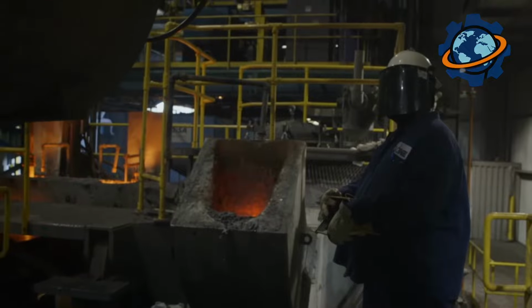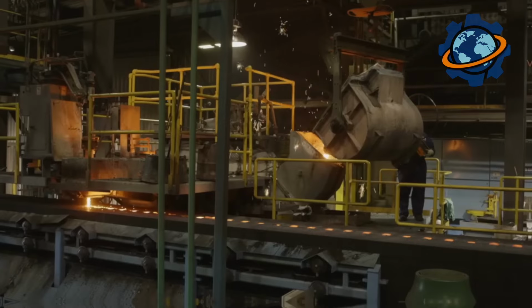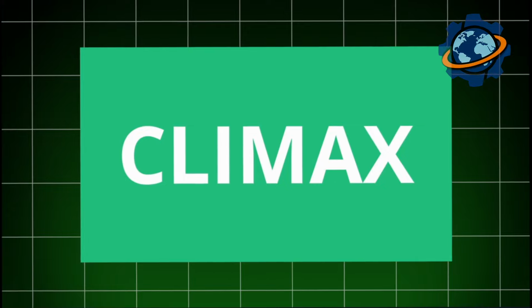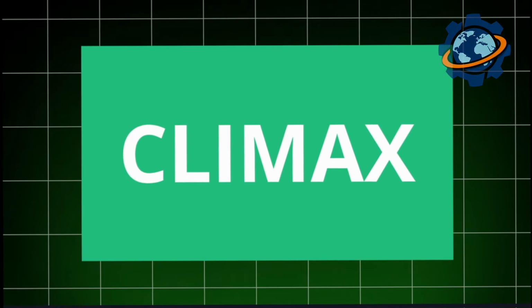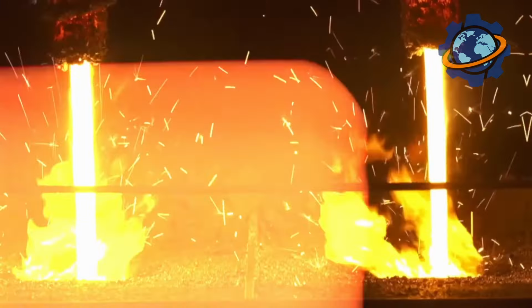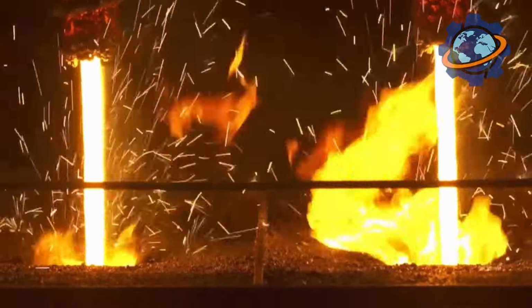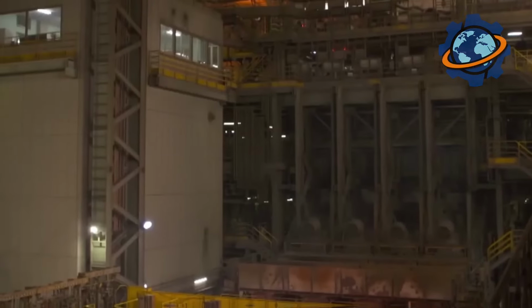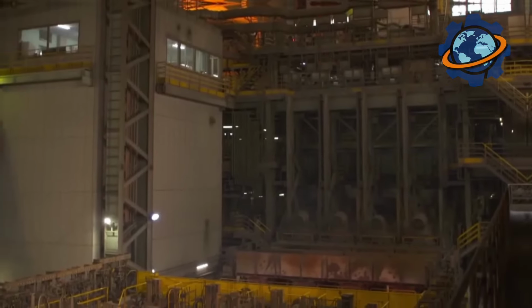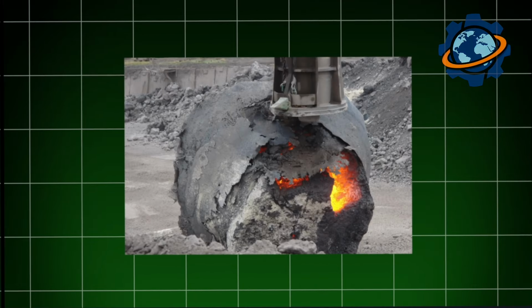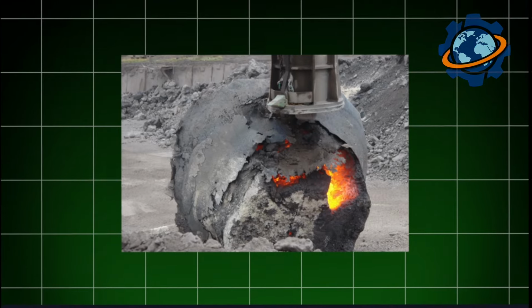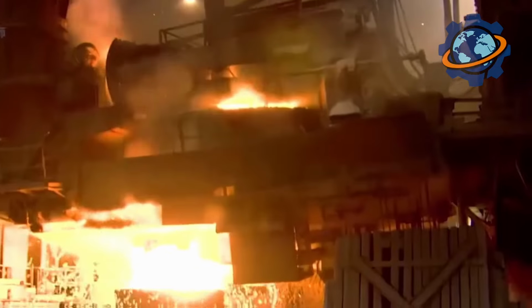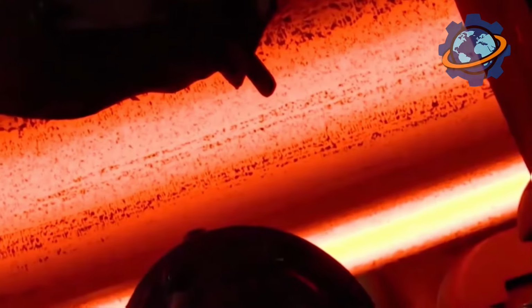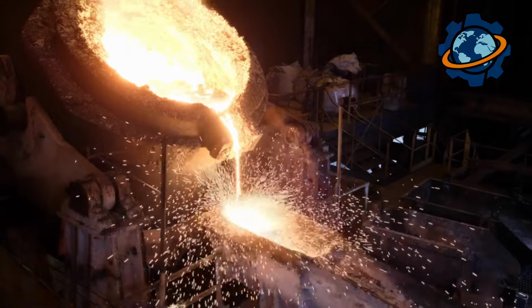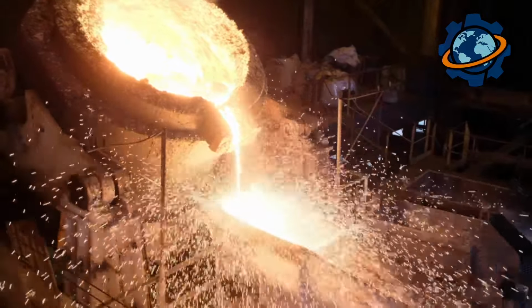Roughly every 40 to 60 minutes, enough liquid products have collected in the bottom of the furnace. It's time for the climax, a truly mesmerizing sight. A furnace worker, the keeper, uses a special drill to punch open a hole in the furnace wall, the tap hole. First, they tap the slag. It's lighter than the iron, so it floats on top. It's a molten, lava-like mass that flows into special ladles. And then they open the iron tap hole, and a dazzling, sparking stream of molten metal erupts with a roar.